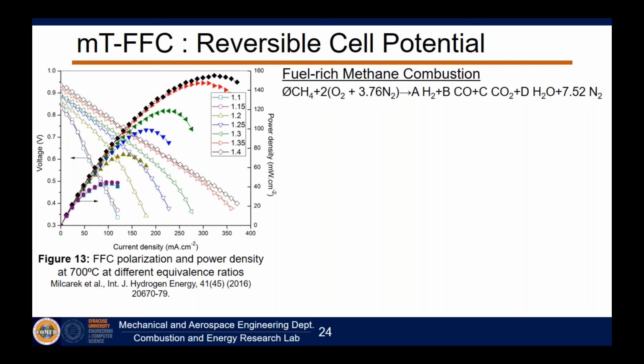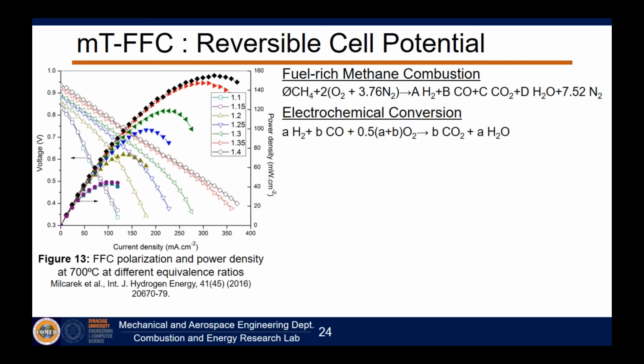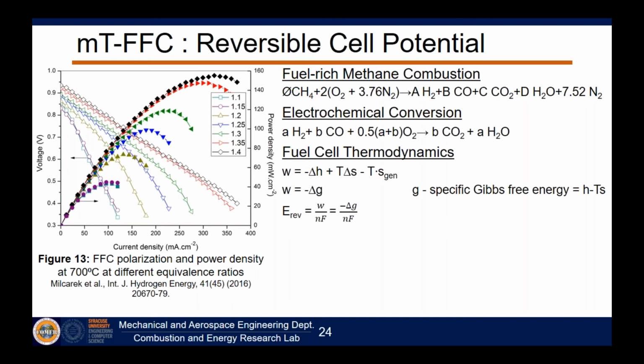Well, we can look at that theoretically. We're taking methane, we're oxidizing it at different equivalence ratios, and we're generating some composition of syngas and other products of combustion. We then realize that not all of those products of combustion are actually participating in the electrochemical reactions. It's only the syngas that's participating. So this is the fuel cell electrochemical reaction. This is what the fuel cell essentially sees. Now we can use thermodynamics, taking the first and second law and combining them together. We realize that the electrochemical work of the fuel cell is related to a change in enthalpy, entropy, and entropy generation.